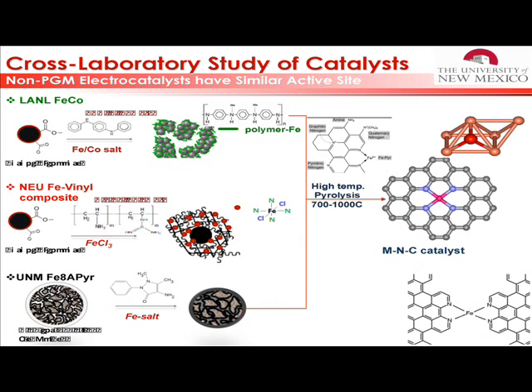Then, in order to deconvolute the XPS spectra, we introduced a method by DFT to compute the binding energy shifts. It is not trivial because usually DFT is working with the outer electron sphere. Here we need to compute the shifts in the K and L electron spheres. And we just published that in ChemComm, how we can attribute individual types of defects in order to be able to model the composition of the XPS spectra.